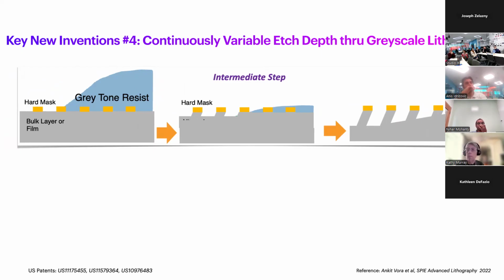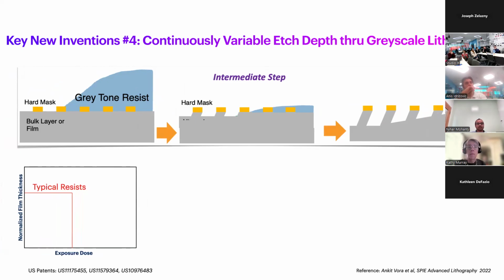But herein lies the problem. Over the past several decades, the semiconductor industry has been developing resists that have a step function response for the dose, which is to improve the line edge roughness or the edge placement errors, because these resists are used to make lines and spaces. What we needed for our grey tone resist for creating this continuously variable etch depth is a shallow and linear dose response, which is completely antagonistic to the decades of R&D for semiconductors.